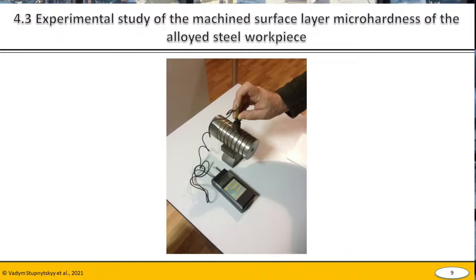The analysis of accuracy of modeling was carried out as a result of comparison with the results of experimental studies. Such comparative results were obtained using the methods of measuring the micro hardness of the surface layer before and after machining. The analysis of research results showed comparability of the surface hardening value obtained as a result of modeling and as a result of experimental research within 6 to 8%. Next slide, please.